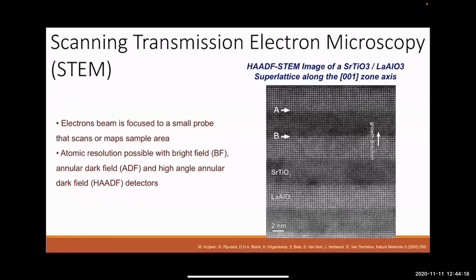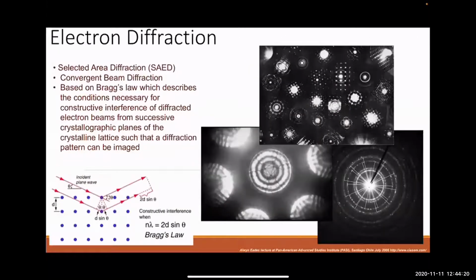So you can also do what's called diffraction. Diffracting off of crystalline materials, you can get all of these gorgeous diffraction patterns that are quite complex and rich with a lot of information. It can tell you, for example, orientations of your crystal, or again, lattice parameters. This involves Bragg diffraction. It can give you the distance between atomic planes.